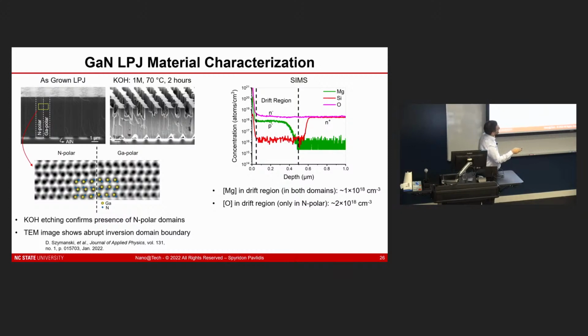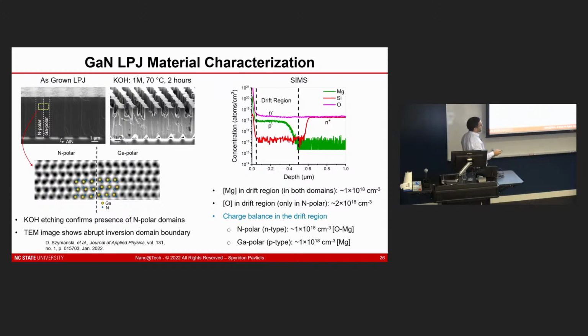And then we're also seeing about 2E18 of oxygen. But we know that there is very low oxygen coming from the gallium polar region. So we can attribute the magnesium from both regions and the oxygen from only the nitrogen polar region, where it is predominantly being incorporated. When you go through and do the math on that, you basically see that you have this charge or impurity balance of 1E18, N-type and P-type, between the two regions. So this was a very happy result for us to see that the doping is being controlled well at these dimensions, and then we're able to move forward with characterizing this device.